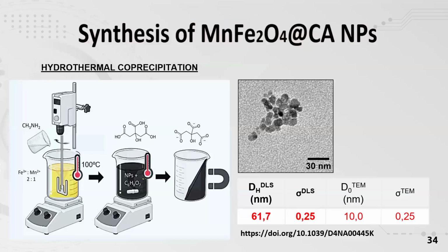This technique involves the precipitation of nanoparticles when a mixture containing iron cations 2+ and 3+ comes into contact with a basic solution. The magnetic nanoparticles were then coated with citric acid, and we obtained a sample of nanoparticles with an average size of 10 nanometers and a round morphology. Now it's time to try them out.